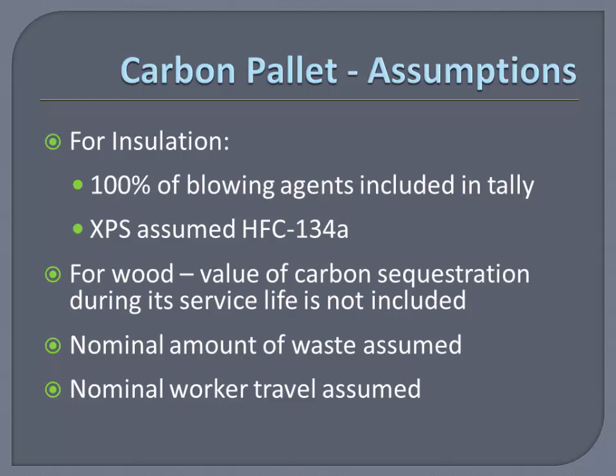I made some assumptions because some assumptions really wildly affect the outcome of the carbon emissions calculations. For insulation, which is significant, I assumed 100% of the blowing agents included in the tally. Does it ever eventually all get back into the atmosphere? It's not clear. And I also assumed that extruded polystyrene uses HFC 134A, which is at this point the most common blowing agent for extruded polystyrene. And we'll see what that means in a slide or two.